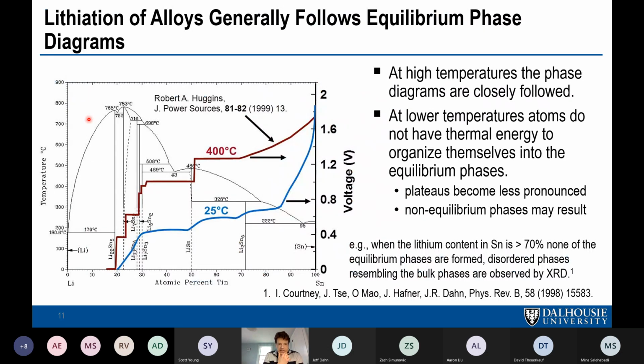The other interesting thing is how these materials lithiate in comparison to their thermodynamic phase diagram, the binary phase diagram of these metals versus lithium. And here I've superimposed some voltage curves of lithium inserting into tin from two different publications. One is by Bob Huggins, who did lots of pioneering work in this area at high temperatures. And then Ian Courtney and Jeff Dahn's lab did a lot of pioneering work on the lithium-tin system at room temperature. And at 400 degrees C, you can see when you lithiate, you get this kind of slopey region here, but then after that, it turns into a horizontal plateau.